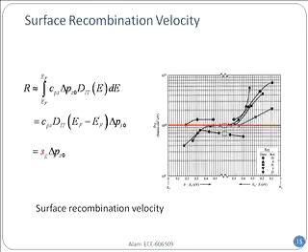People will say, oh, I have done a new processing, but my surface recombination velocity is horrible. They made a measurement. So let's say they will shine light and they'll see how the current is decaying. And from that, they will extract back the rate R on the left-hand side. And from that, they know what this delta P is. So they will extract back a surface recombination velocity. If it is horrible, that means they have to do something to the surface, because the surface is still not good enough for good electronic devices. So bottom line is, somehow or other, suppress S sub 0 by improved processing, right? That's something one has to do.